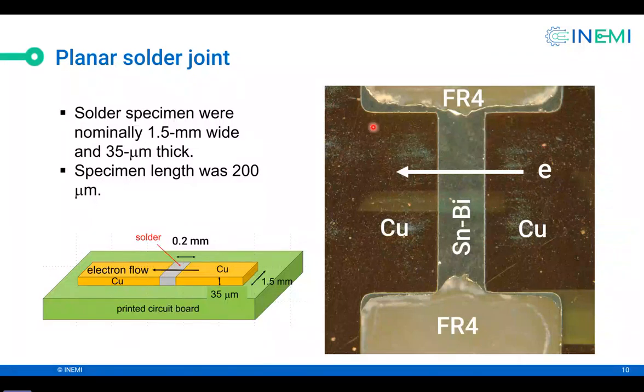So this is a top view of a tin bismuth planar solder joint. So we're looking down, and the thickness of this film is about 35 micrometers. So here's copper, here's the solder, here's copper, and current is flowing in this case from right to left.